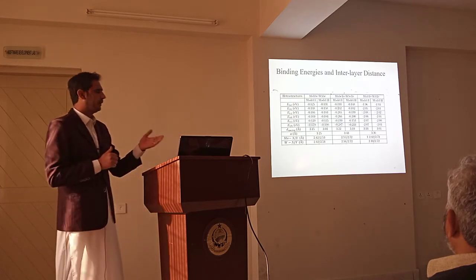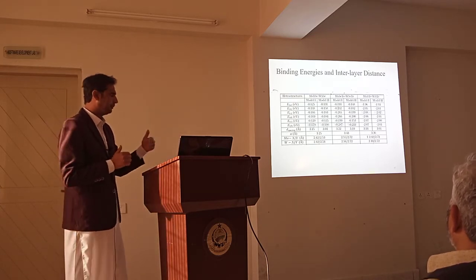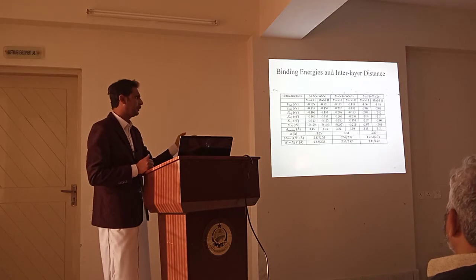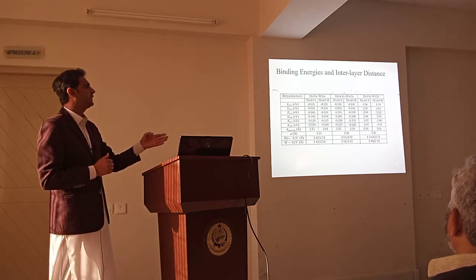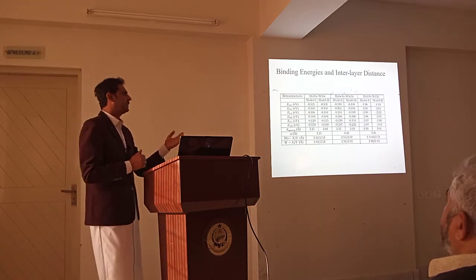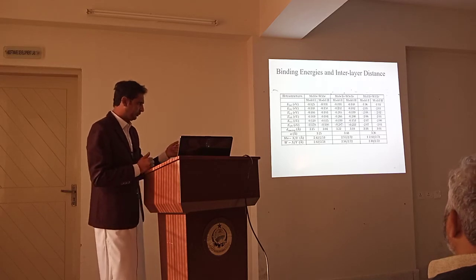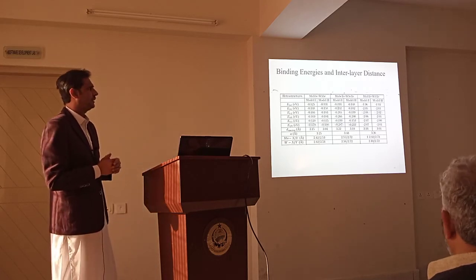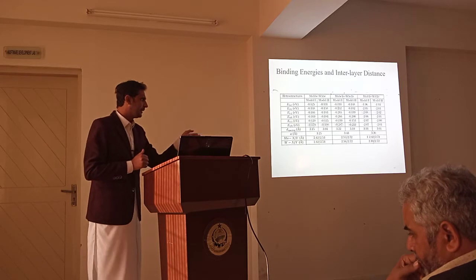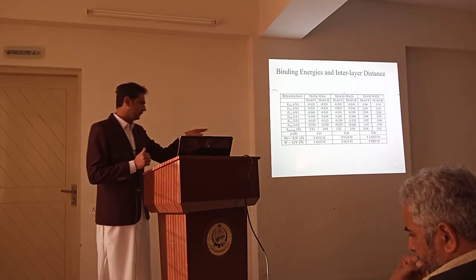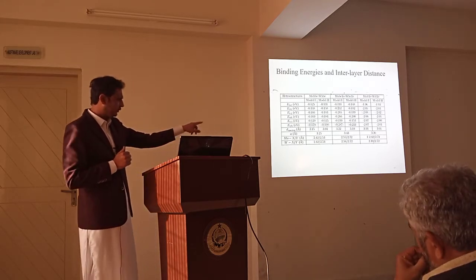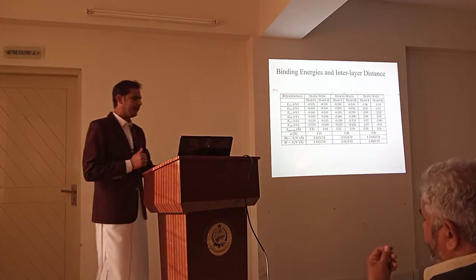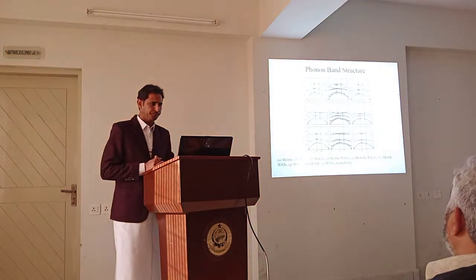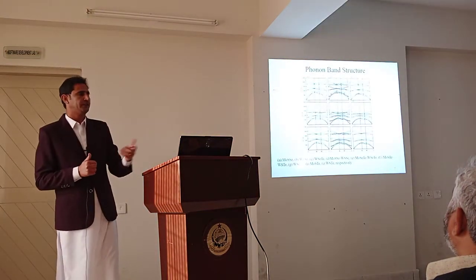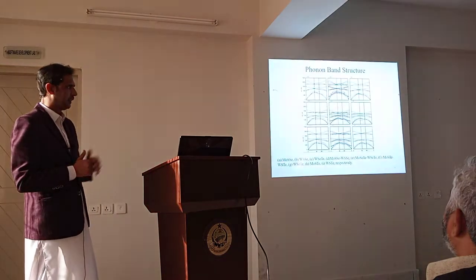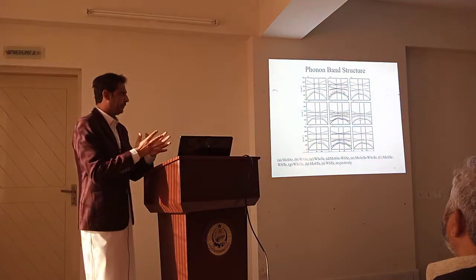Here d represents the interlayer distance, the lattice constant, which is 3.25 for MoSSe and WSSe. For both models, MoSeTe and WSeTe, it is 3.43, and 3.36 for both models. Here MoX/Y, WX/Y is the bond length of this van der Waals heterostructure. To further confirm this stability, we have calculated the phonon band structure of this stable configuration.